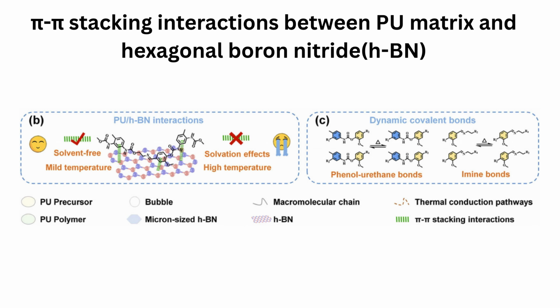Aromatic moieties in the PU matrix derived from toluene diisocyanate (TDI) physically adsorb onto h-BN surfaces through pi stacking interactions. Leveraging the material's reversible characteristics, the composite achieves a 95% healing efficiency. Although pi-pi stacking interactions endow self-healing polyurethane with highly efficient self-repair capabilities, such materials still suffer from inherent limitations, including low mechanical strength, insufficient modulus, and the requirement of external stimuli to trigger the healing process.